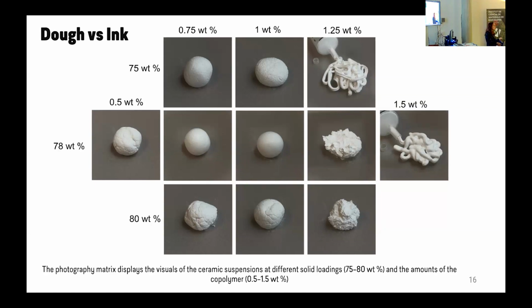I don't know if there is anyone who is doing robocasting or direct ink writing with ceramics here. But the idea is to put as many ceramic particles as possible into the system, but it still flows as if you are getting it out of a syringe, a toothpaste kind of idea, right? So the idea over there is to put as many particles into the system as possible, because once the filament is printed, you would like it to be robust, because now you need to introduce the second layer, third layer on top, so it should be able to carry the weight of the consequent filaments in the system. So at those times we were designing these ceramic inks with lots of loading, such that we produce nice filaments. And that is how we got into this dough business as well.